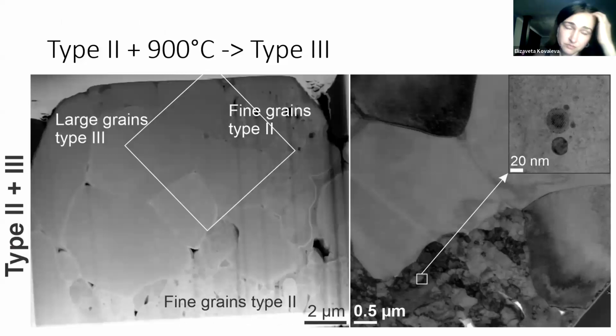So we made a FIB foil, and we see that these large, clear grains with curved boundaries are sitting in a groundmass of smaller grains, which have inclusions of zirconium oxide, which tells me that this grain had a long history of recrystallization, so it was decomposed, back-reacted, and then recrystallized again. And probably if we date this grain, we will get the age of the impact structure. So this is, I think, also from the Araguainha impact structure.